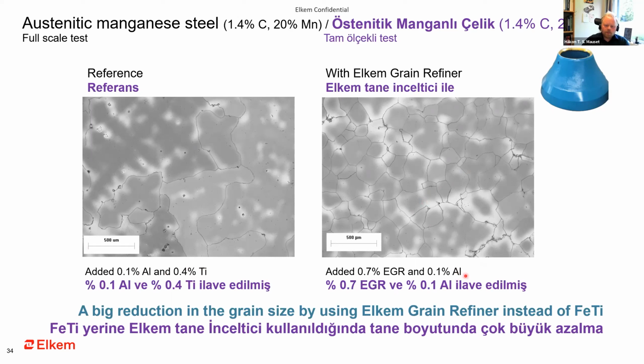And then we did some trials where we kept the aluminium, but we skipped titanium, and then we added 0.7% of EGR instead. And then you can see that the grain size is substantially smaller. So here we have a really big effect of the EGR.